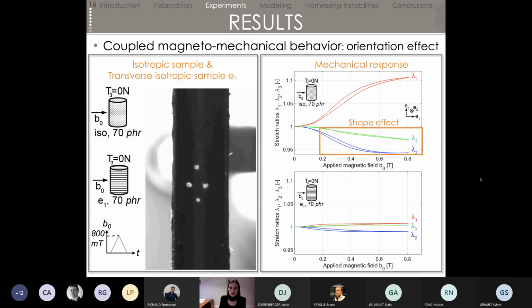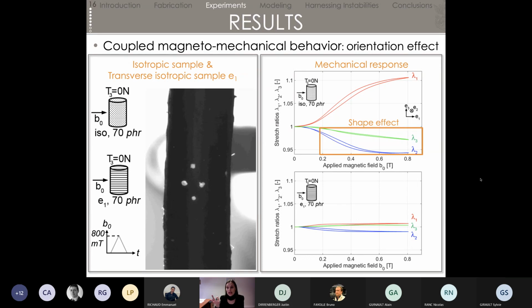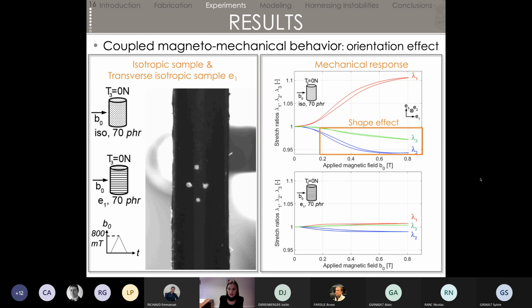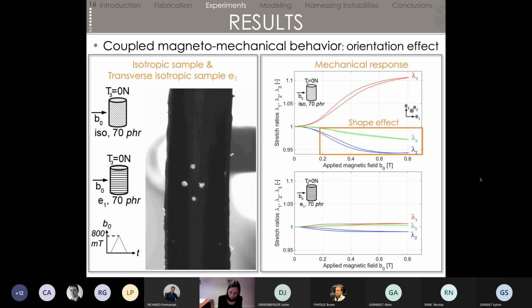Another point that was interesting, and we need to note, is that my sample is isotropic. I put the magnetic field horizontally, and I have large strains in that direction. But the other two directions, E2 and E3, should behave the same. But they don't here, as we can see, and that is due to the fact that these materials suffer from shape effect. Here our sample is elongated, so we don't have the same overall dimension in the other directions, namely the vertical direction and the transverse direction in the plane, and this affects the way things deform. That's the shape effect I'll come back to later.